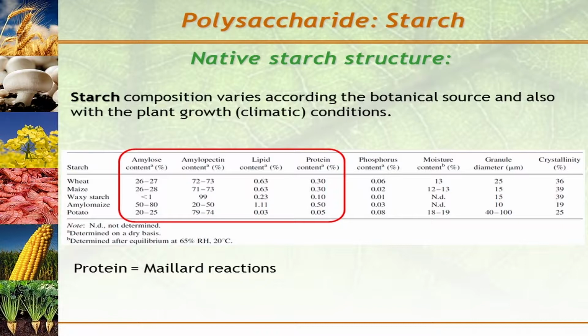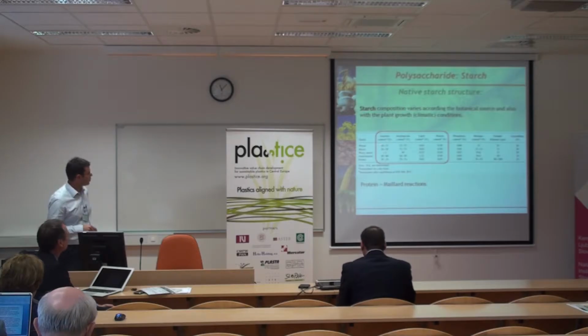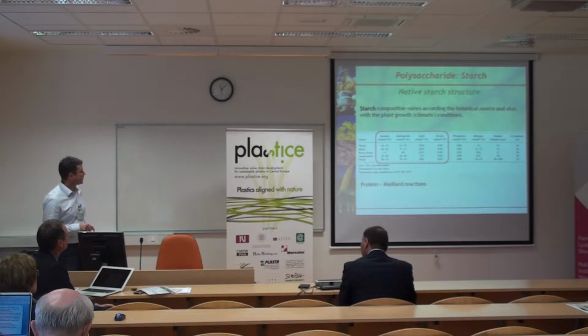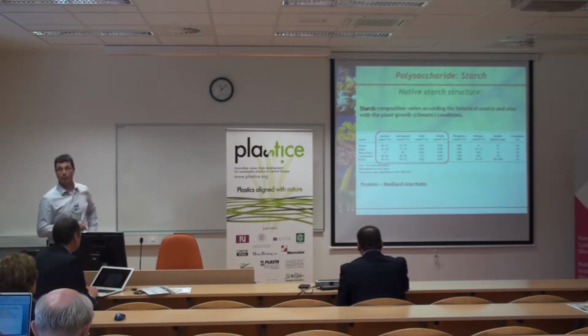So depending on the botanical source, this ratio between amylose and amylopectin may vary a lot, and also from one type of vegetable, one type of plant, it may slightly vary depending on the place it has been grown, on the climate conditions, and so on. So here you have a few examples where you can see that wheat starch contains about 25 to 30 percent amylose, and slightly more than 70% amylopectin. But waxy starch, for instance, can reach up to 99% amylopectin, almost integrally amylopectin. And amylomaize has up to 80% amylose and a lower content of amylopectin.